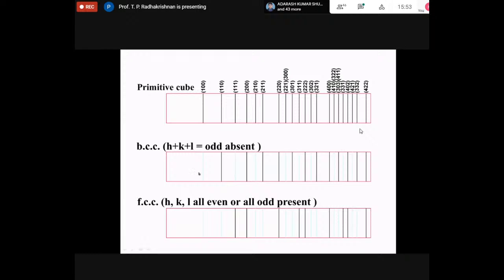Now, this looks like a very mysterious thing, but these are called systematic absences. It is not coming due to any particular type of atom present, but due to the symmetry of the crystal lattice. How do you know this? And how do you understand the meaning of systematic absence? Because by now looking at this pattern of the sodium chloride crystal, I can immediately tell not only does it belong to a cubic system, but because of these systematic absences, it belongs to an FCC system, not a BCC. Now, the only thing I have not told you is why it happens to have these missing lines and why sodium chloride with an FCC lattice gives you only certain particular conditions. So I can now come up to the level of not only the crystal system, but also specify which Bravais lattice it belongs to by doing a powder diffraction experiment.